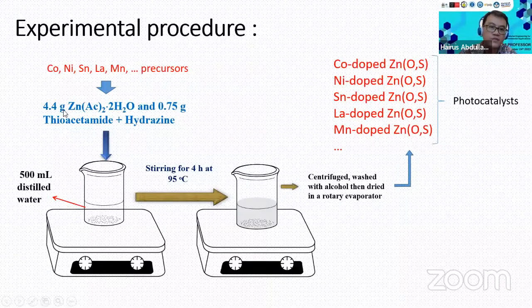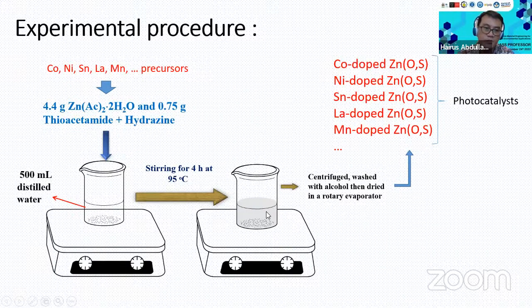You just use zinc acetate as a precursor, and then TAA as a sulfur source, and we dissolve them in 500 milliliters of DI water. Then during the heating process, until 95 degrees, we add hydrazine as a reducing agent. Finally, after 4 hours, we can see a white precipitate. This is what we call the Zn(O,S) material.